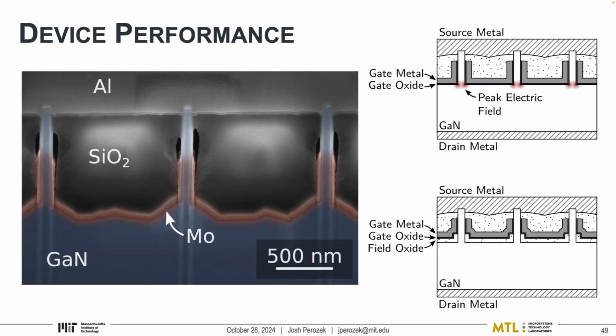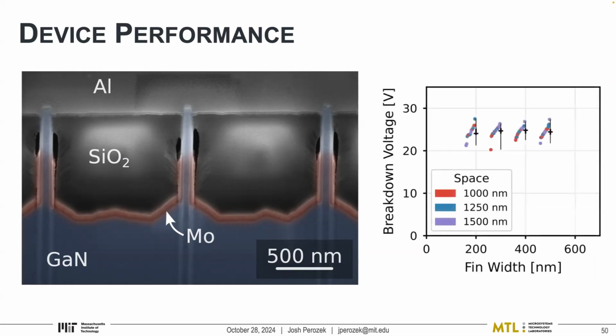What we can do is put in silicon dioxide. It's very strong. It can handle high electric fields, and it kind of reduces the effects of that corner. We didn't have that, so all of our devices broke at 25 volts, as expected. That's the breakdown voltage of our gate oxide.